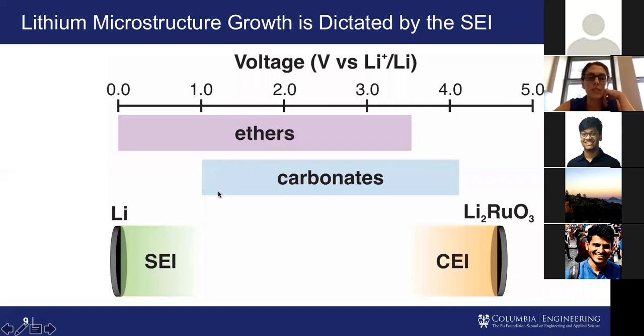What this means is that when you start operating the battery at low voltage, you have decomposition of this electrolyte material, and it forms something called the solid electrolyte interphase on the surface of lithium metal. The structure and the composition of this decomposition layer is what we think is actually dictating this microstructural growth that can sometimes grow out of control and cause these very serious safety concerns.